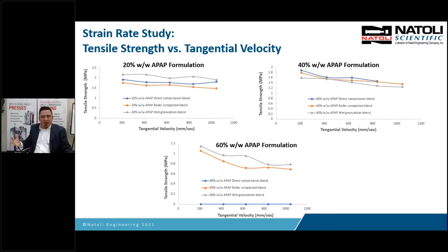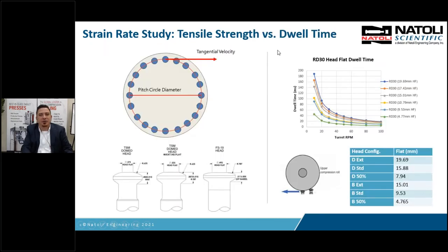Not tablets per minute. I ran this at so many tablets per minute, now run this press at that many tablets per minute. That's not how you scale up. You don't want to use RPM either, and you can use tangential velocity. You can also use something called the dwell time. And the dwell time's been used for, I don't know, probably a century. The dwell time is the time in milliseconds that your punch head flat is under the compression roller.